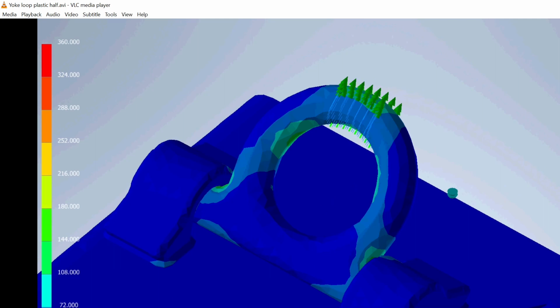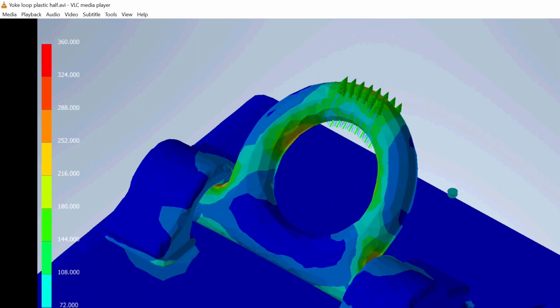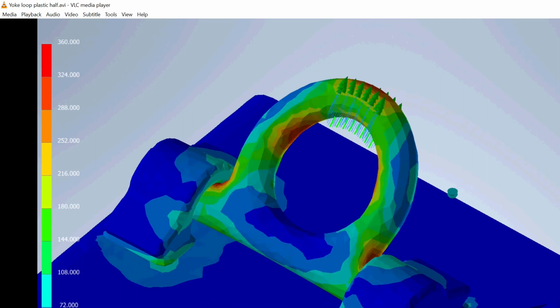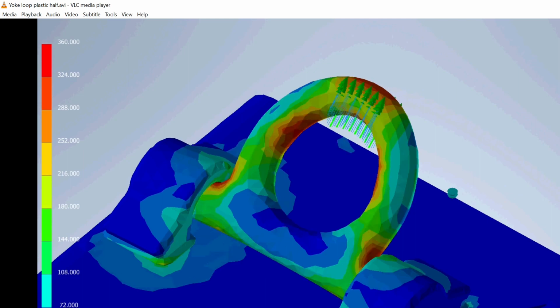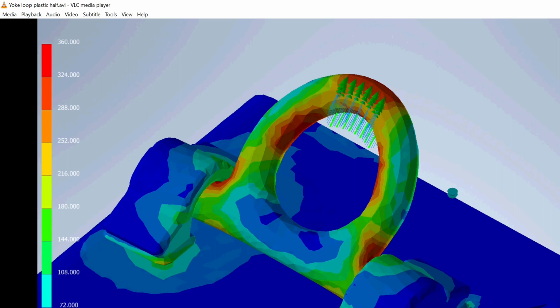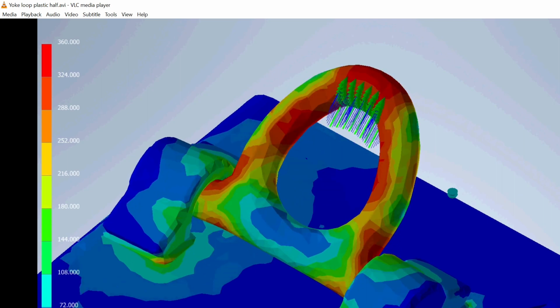And the main reason for doing this is to see if the welds are going to hold. So I had to draw the welds and the attachment points. And the conclusion of this analysis is that the component is not safe for when the load is full. You can see these red areas which are at risk of failure in a way.